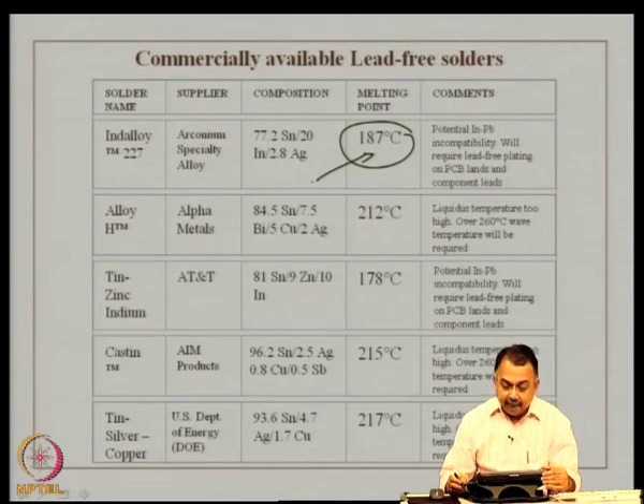There are problems like potential indium lead incompatibility, will require lead free plating on PCB lands and component leads. So, the preparation of your PCB surface has to be tuned if you are using this kind of a material. Then Alpha Metals produces alloy HTM, where it is tin, bismuth, copper, silver, 212 degree centigrade, and liquidus temperature is too high,